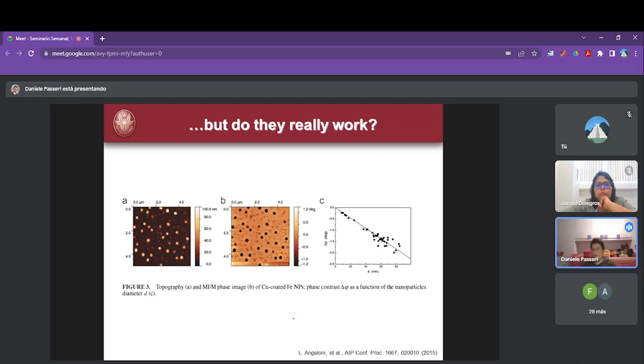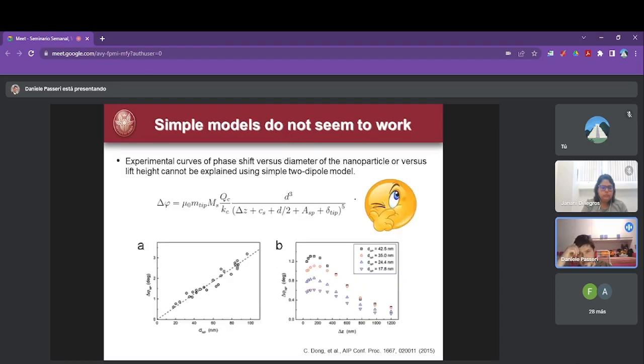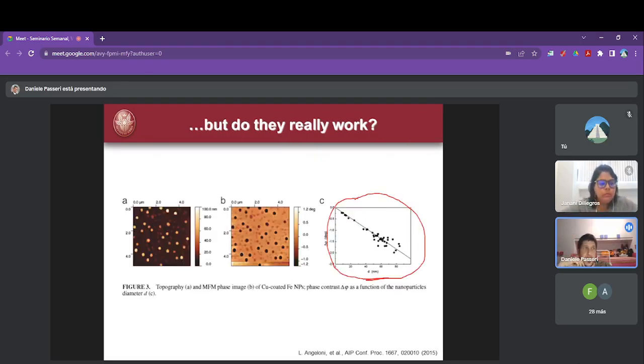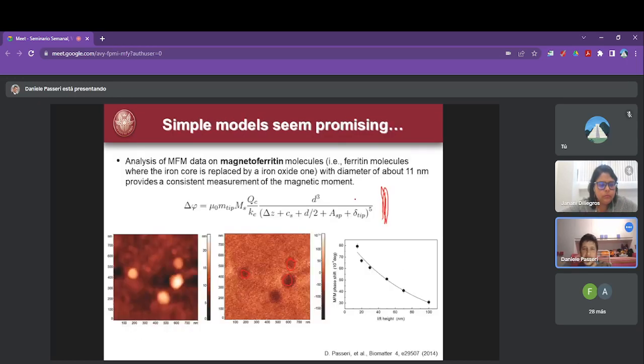But the problems were much more than this, because we did the statistics on many nanoparticles. You see, this is the phase shift depending on the diameter. And you see, wow, there is a very good linear relation between the phase shift and the diameter of the nanoparticles. Oh, sorry. But really, this model does not foresee a linear behavior. Here you have the cube of the diameter.